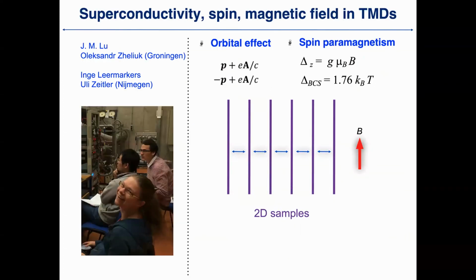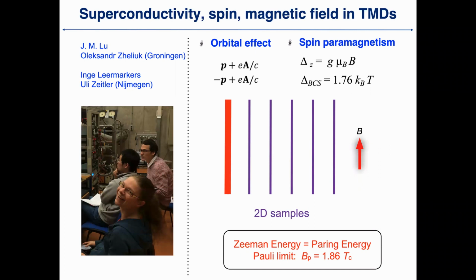So having these two features, we can actually study the system. One point is that because we can isolate the electronic system, we can study the superconducting property. And why this is very nice is because we can suppress the orbital effect, because if we apply a B field in the direction along the plane, then we can suppress the orbital effect. So then we can study the spin paramagnetism only, and the spin paramagnetism can be gauged with the energy of the gap, so that the one parameter we have for this spin paramagnetism is something called the Pauli limit, and the Pauli limit is roughly scaled as 2 times TC with a unit conversion.